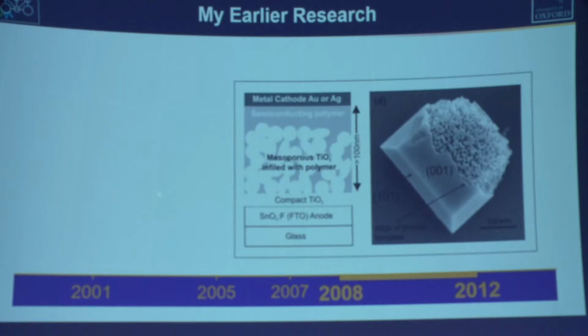We went another step further and actually made porous single crystals. This is an example of a single crystal of titania, which is solid on one side and porous on the other. We actually wanted it to all be porous. This was a crystal that didn't quite grow perfectly, but it illustrates it quite nicely.